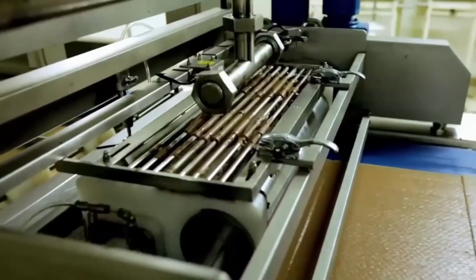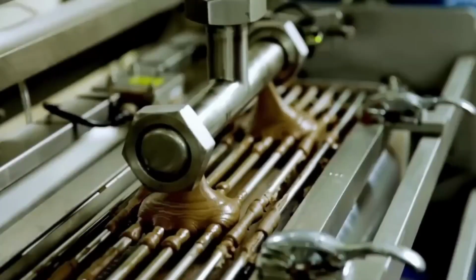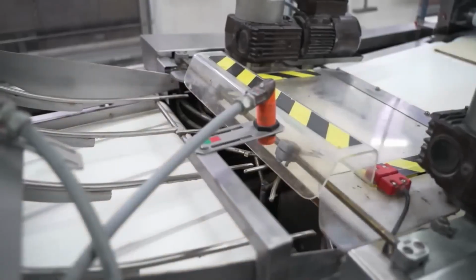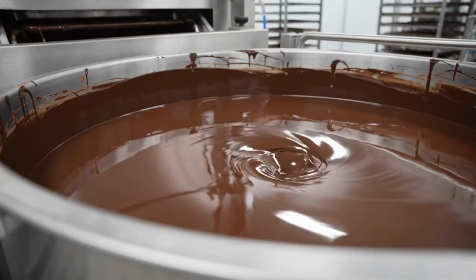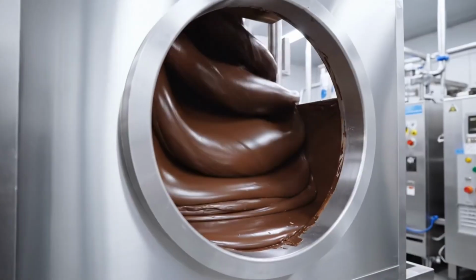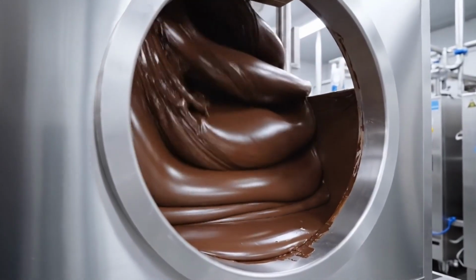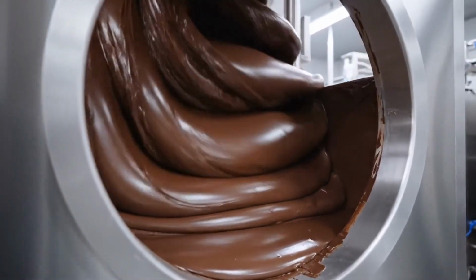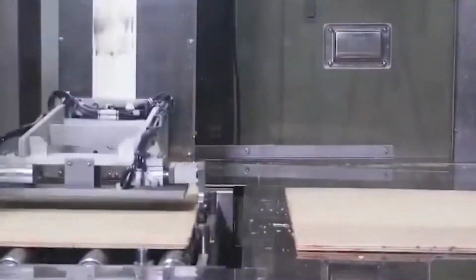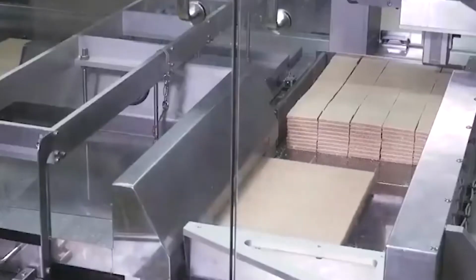First, the chocolate is fully melted at 50 degrees to eliminate all existing crystal structures. Then it is cooled to 27 degrees, the temperature at which Form 5 crystals begin to nucleate. Then it is reheated to 34 degrees to 32 degrees, which melts the less stable Forms I through IV that also form during cooling, leaving only Form 5 seed crystals in suspension.